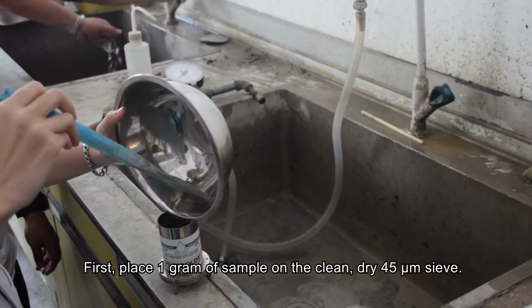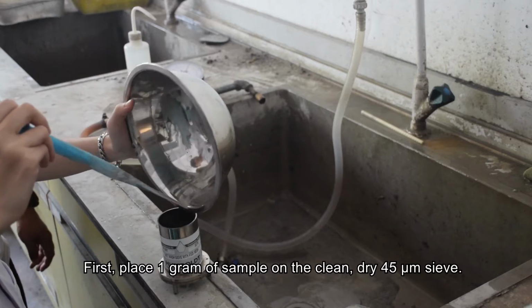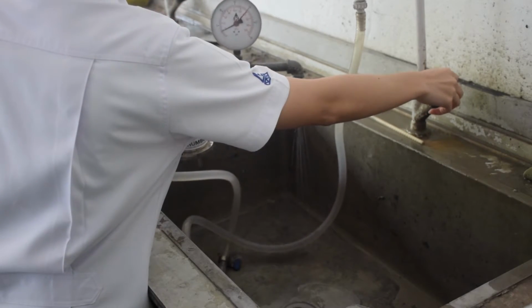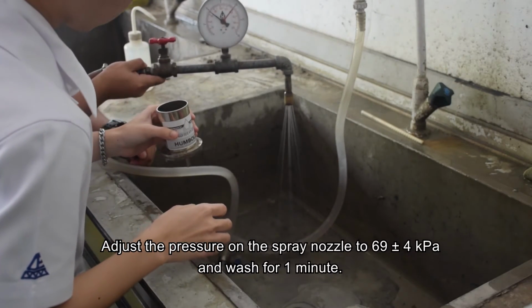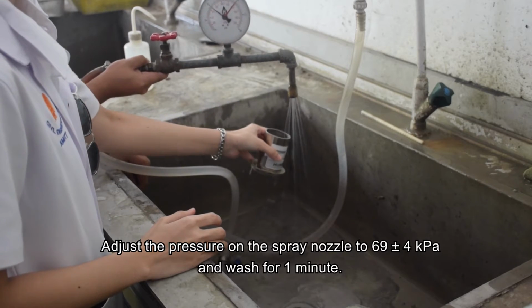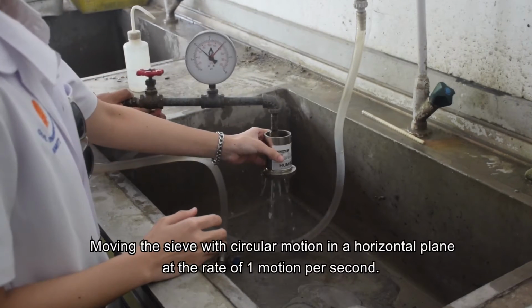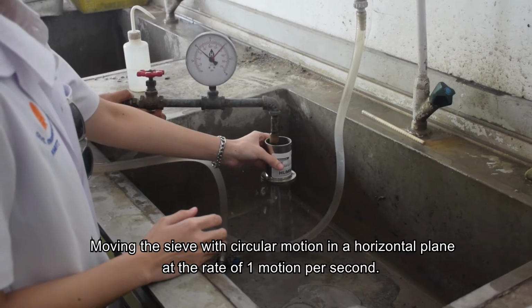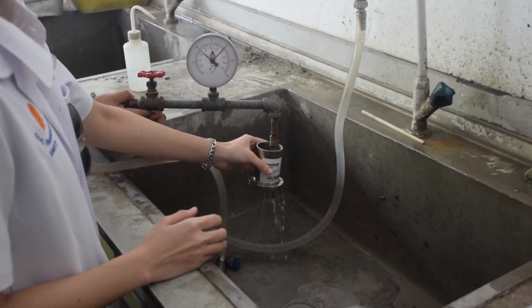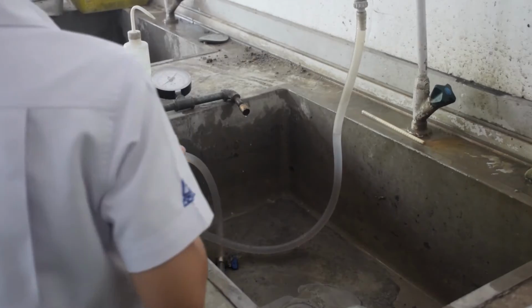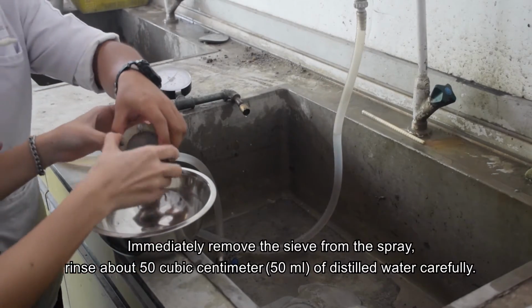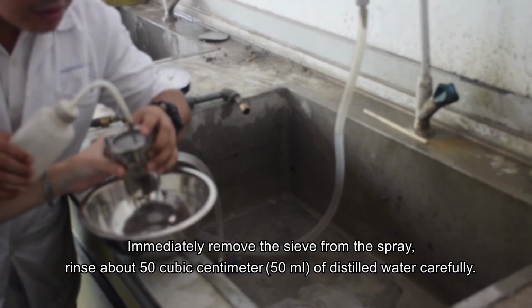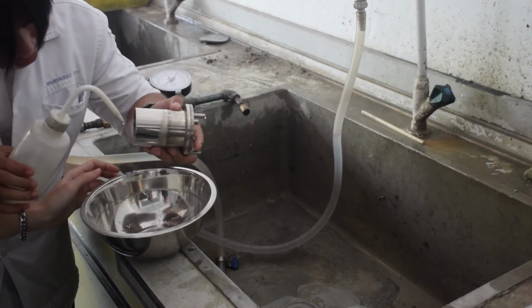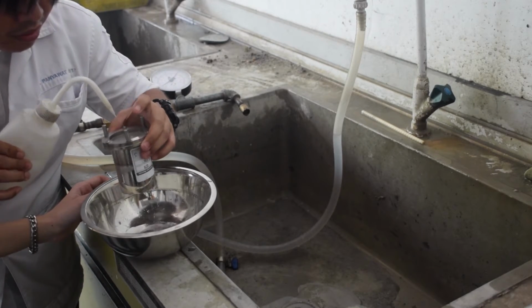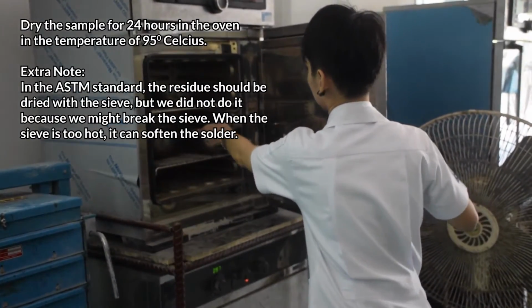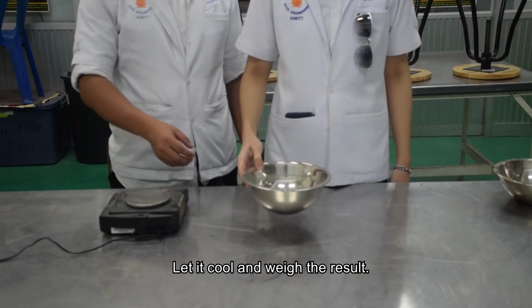First, place 1 gram of the sample on a 45 micrometer sieve. Wet the sample gently with a stream of water. Adjust the pressure on the spray nozzle to 69 plus or minus 4 kilopascals and wash for 1 minute. Move the sieve in a circular motion in a horizontal plane at the rate of 1 motion per second. Immediately remove the sieve from the spray, and rinse with about 50 cubic centimeters of distilled water carefully. Dry the residue in the oven. Let it cool and weigh the result.